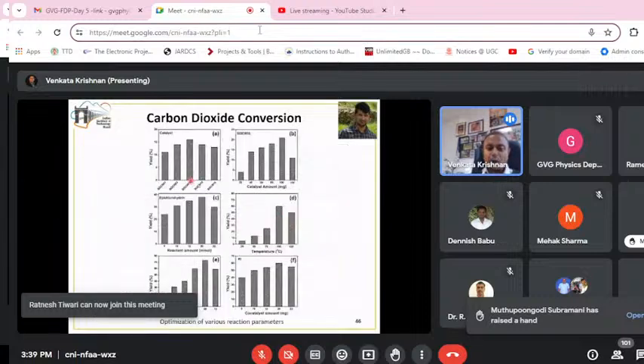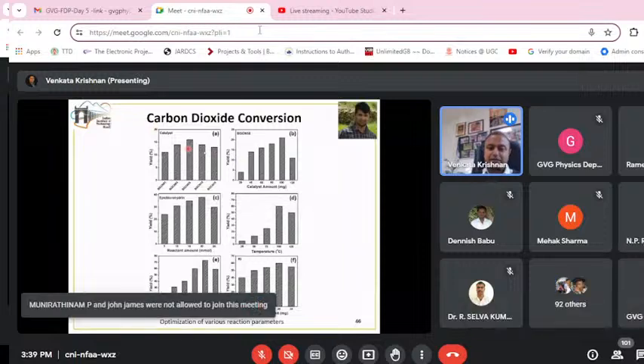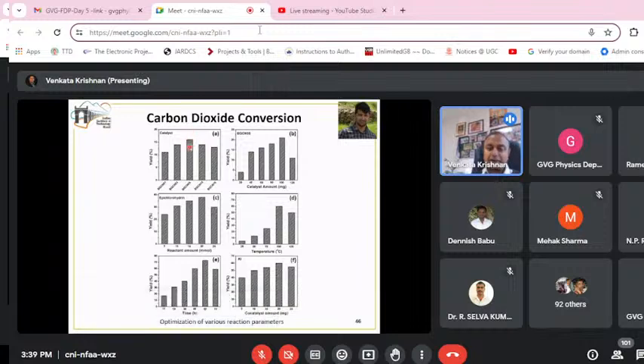Then we did a detailed optimization of the catalytic process, wherein we first optimized the catalyst, and found that 5-8% of the boron-doped graphitic carbon nitride is giving the best result. Then we optimized the catalyst amount, and we saw that 100 milligram is the optimized catalyst amount.